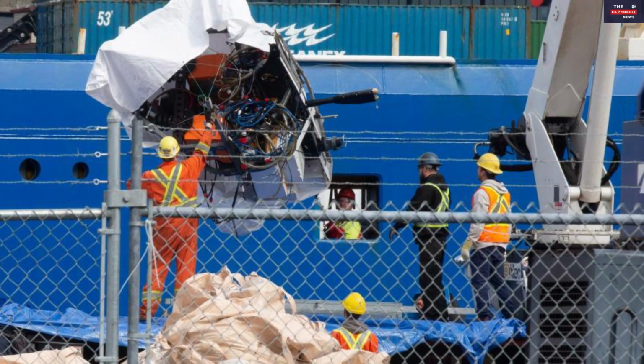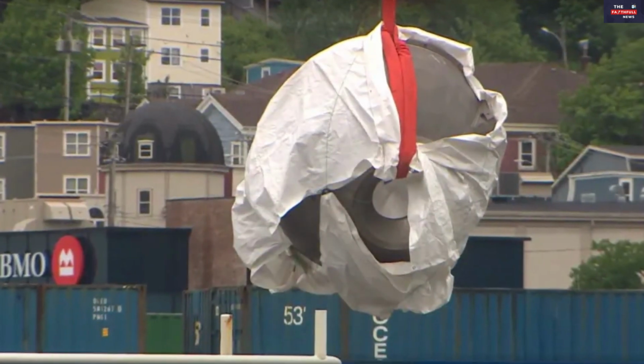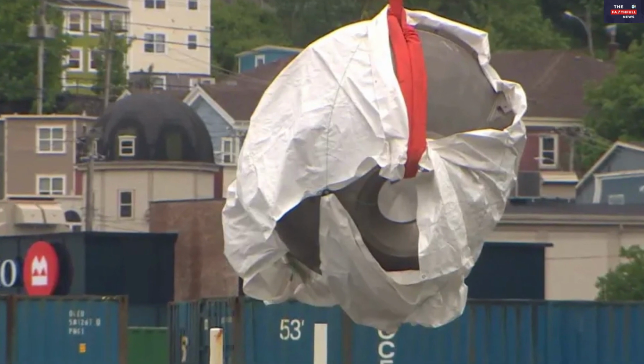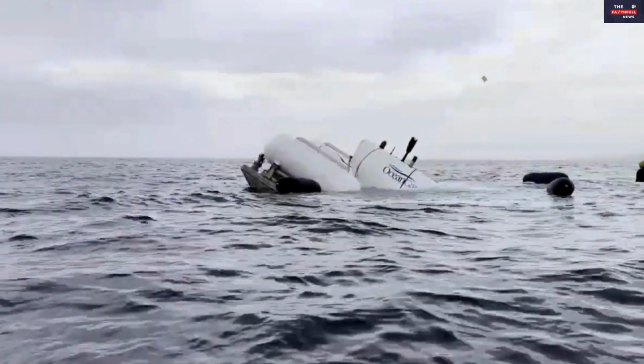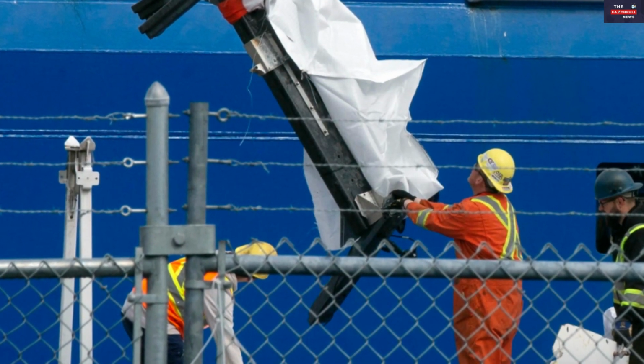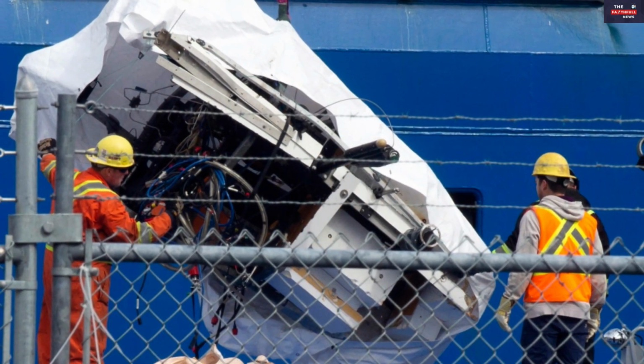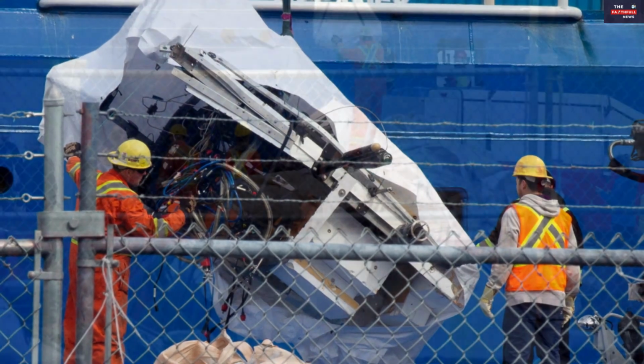Tiny grooves along Titan's surface. Striations in the surface could also tell experts how much time was between the first crack's formation and critical failure of the submarine. Striations refer to tiny grooves or cracks that run in parallel to each other. Dr. Graham Jones said, once a fatigue crack has initiated, it grows a small amount with each loading cycle, typically producing striations on some parts of fracture surfaces. Each striation shows the distance between each stress cycle and time to critical failure.